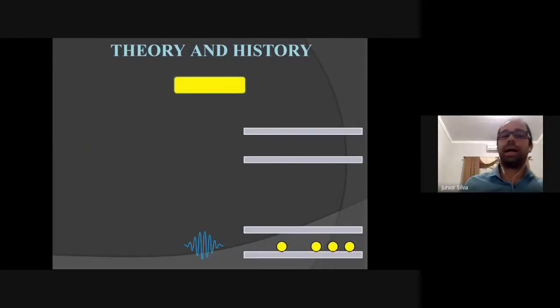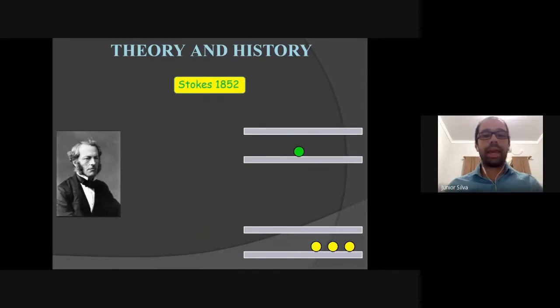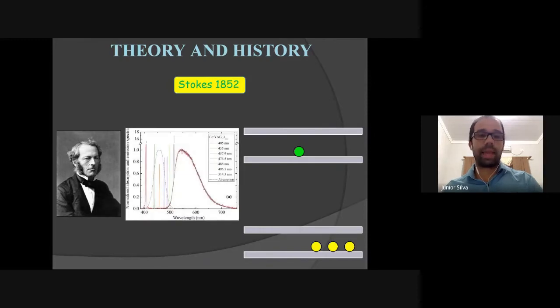But how does this system work? We need to go back to Stokes in 1852. And Stokes said that when we pump the material, we excite the electron, and when it returns to the ground state, it emits light with lower energy, like in this spectrum. Here is a real situation, a Ce:YAG crystal. We pump that line, as we can see in the figure. It's the pump of some lasers, and we pump the material with higher energies, and we can see the luminescence with lower energies, as Stokes said before.